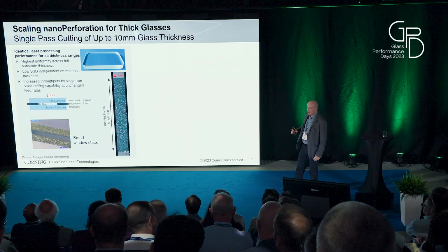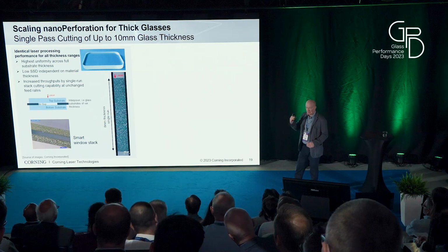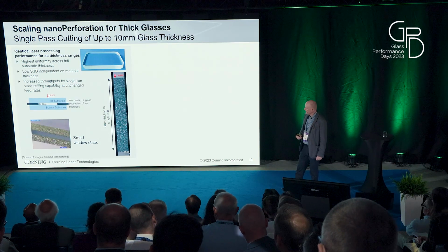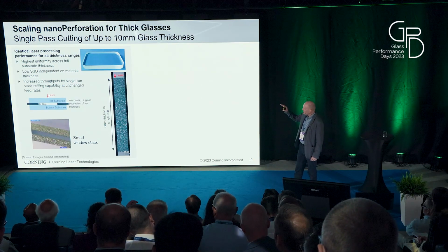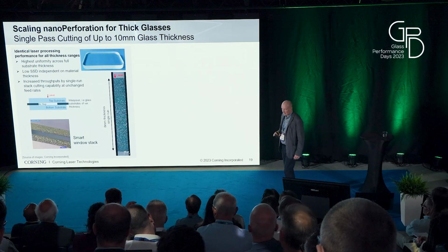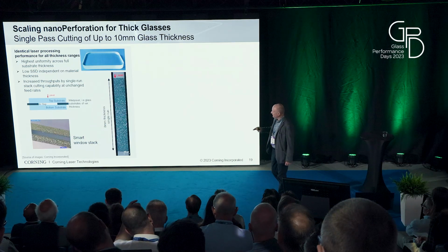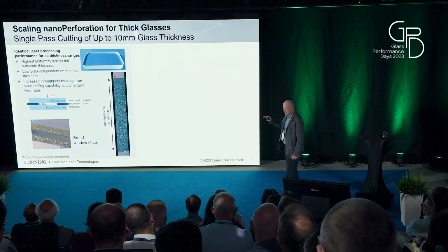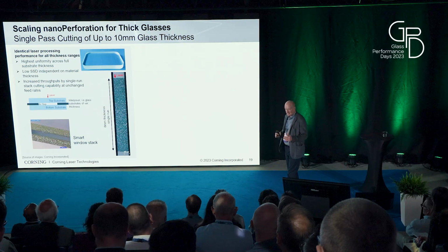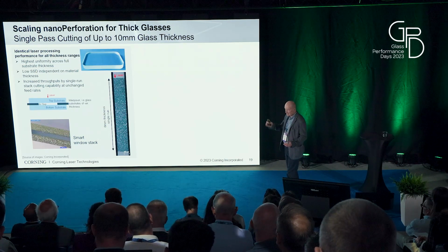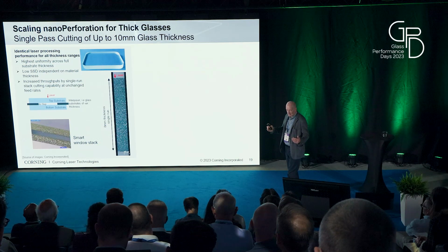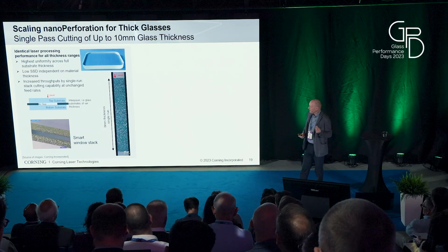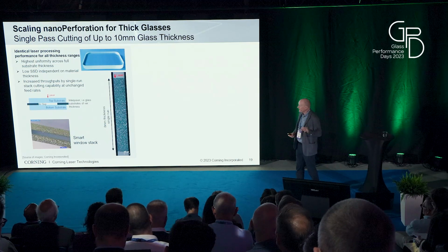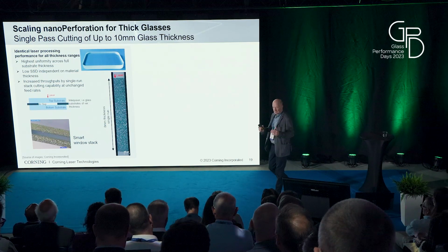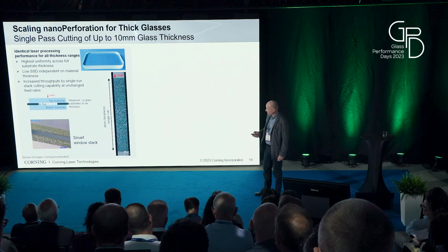And with that, we scaled our technology. That means also adapting the beam shaping design so that we now can cut thick glass up to 10 millimeter, or in the lab even 12 millimeter, but up to 10 millimeter in a single pass. That means we are as fast as with thin glass. We also achieve this up to 1 meter per second speed. And also the nice thing here, we have the same high uniformity, the same low subsurface damage as with thinner glass or with the low power version.